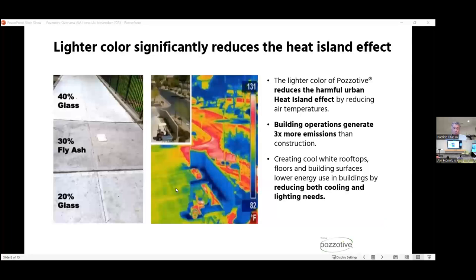This visual, I think, gives you a sense of what it does to lighten and brighten cement. This is two full blocks of New York City sidewalks we did with New York City DOT as a pilot pour. The bottom 20% glass replacement, the middle 30% fly ash replacement, and the top 40% glass replacement. You can see how bright and white it made that top panel. And it just helps reduce heat island effect by making it brighter and lighter. It also creates cooler roof white tops for floors and building surfaces, lowering energy use for cooling and lighting as a result.